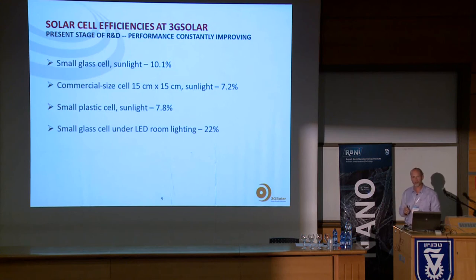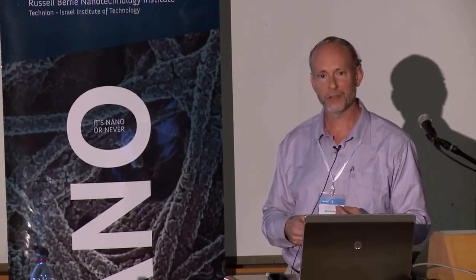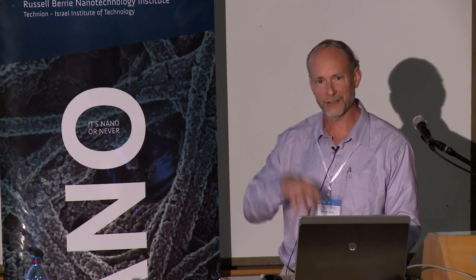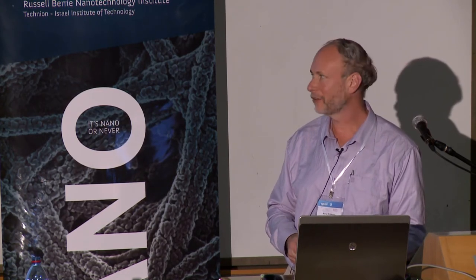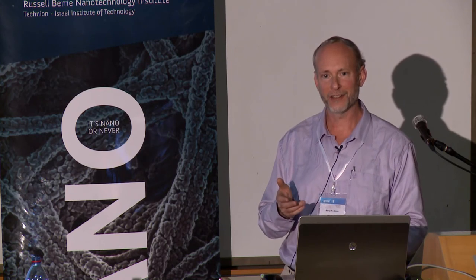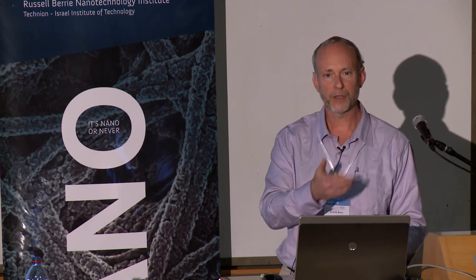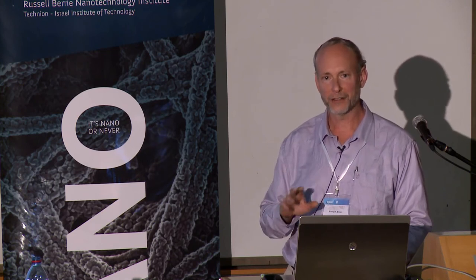Another very interesting result relates to intrinsic characteristics of dye solar cells. We're interested in building integration so full-sunlight performance and long life are important, but we also have the ability to generate current highly efficiently under room lighting. This means the cells can be used inside buildings to charge low-power electronics — much better than silicon. Silicon drops dramatically in efficiency under low lighting, whereas our cells make use of the spectral characteristics of LED and fluorescent lighting, actually boosting efficiency. Applications include wireless security cameras with a rechargeable battery that never needs changing.